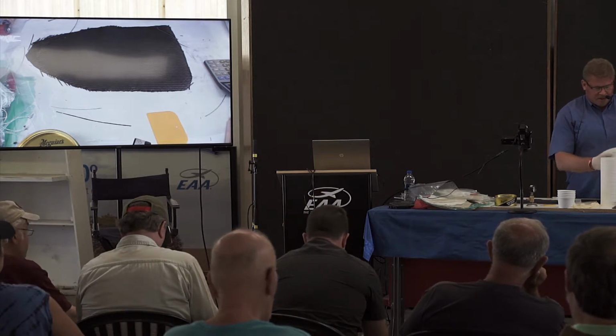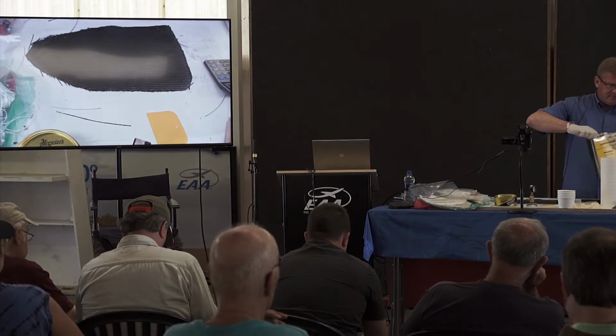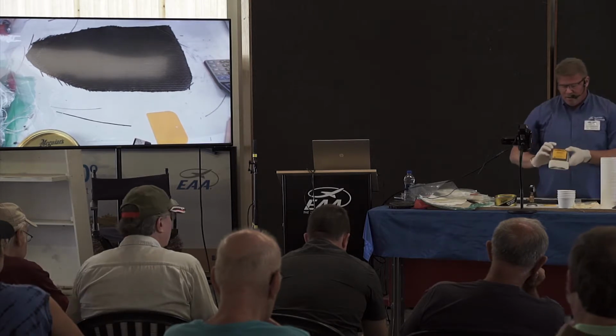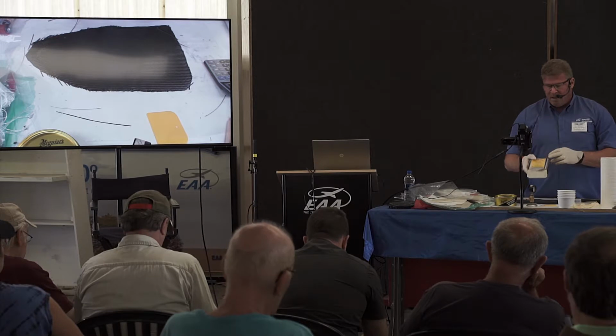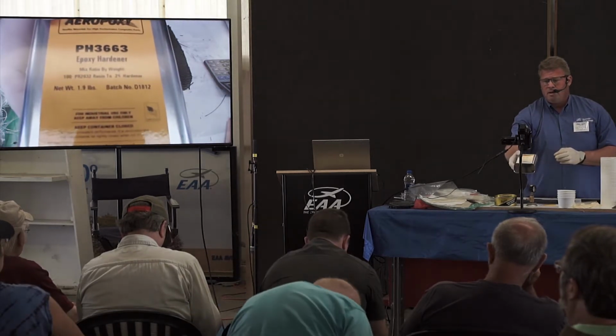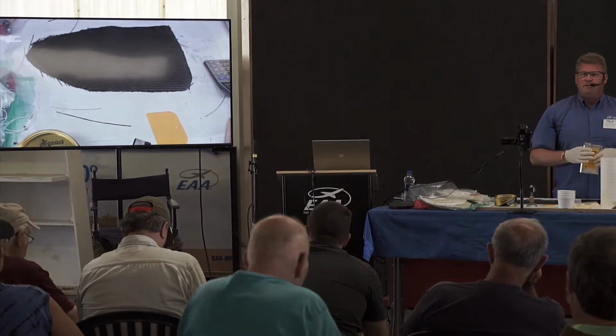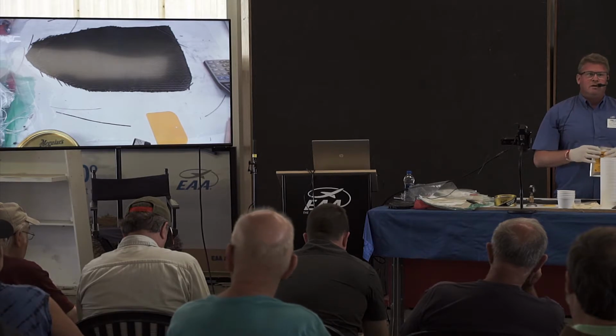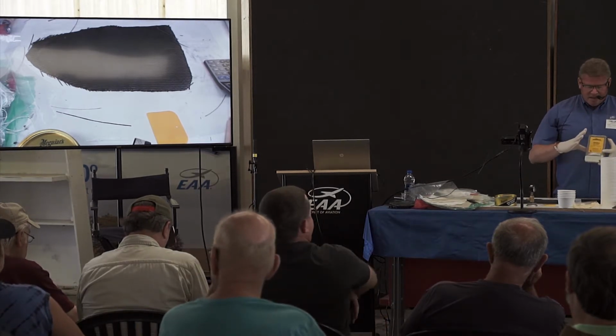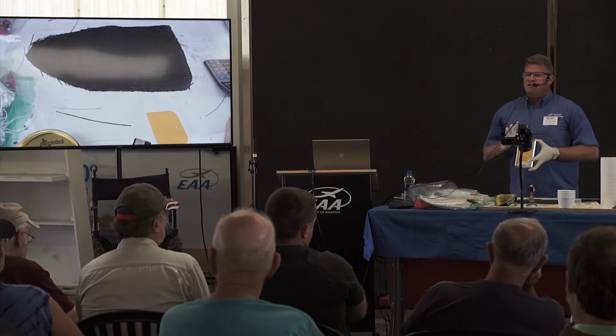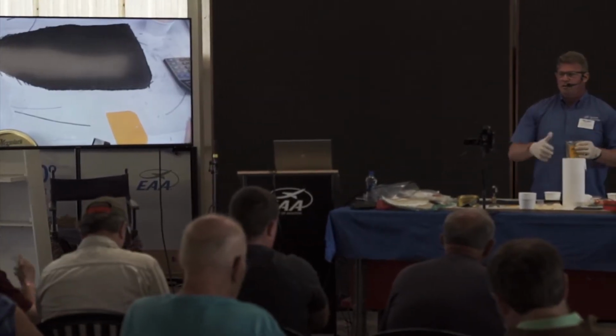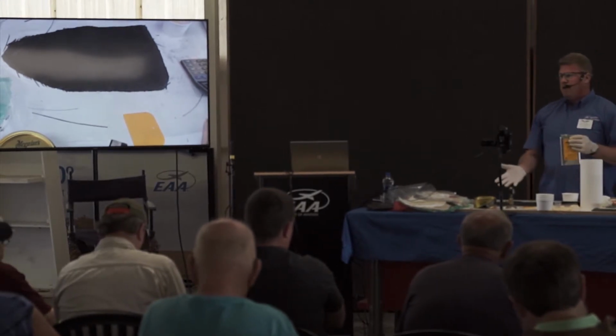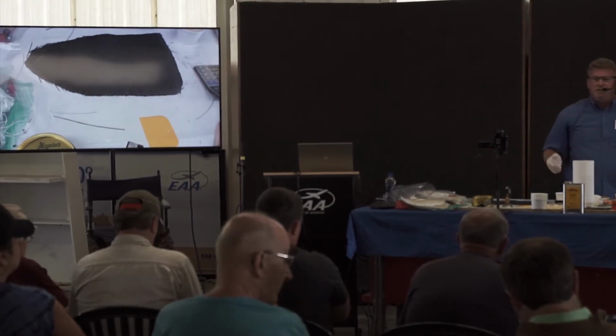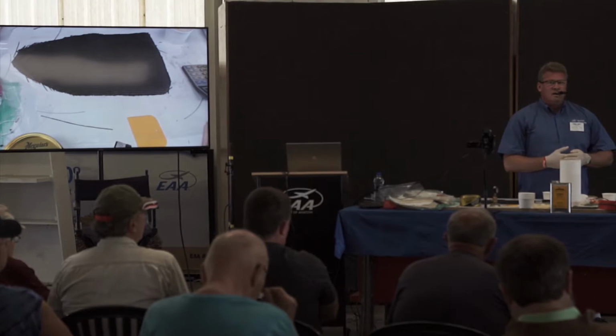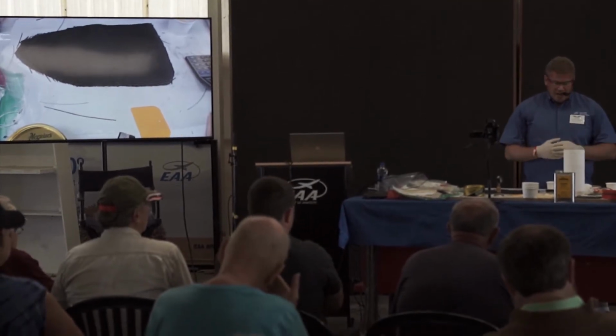So what I'll do is I'll just put some of the resin into this cup, grab the hardener, and for today, this is one of their newer hardeners for this resin system. It's the 3663, and this is a 90-minute pot life, so I've got plenty of time to lay this up and not worry about it cooking off in the cup or starting to solidify. And the reason I like this also is if you decide to get into vacuum infusion, this is a very thin epoxy. When you mix it up with the resin, it's a very thin hardener, and you have adequate working time, because if all of a sudden you're doing all this stuff and it starts cooking off in the cup, it takes a while to put these bags together, and if it starts heating up, you're basically working against the clock. So it's really important to use a hardener with a resin system that gives you adequate working time.